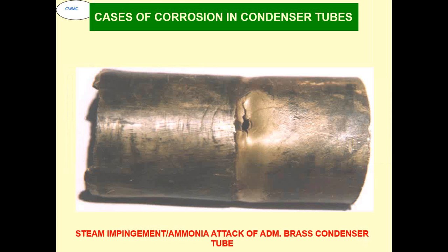This is the steam impingement plus ammonia attack on admiralty brass condenser tube. Normally, on the boiler side, we give a treatment of ammonia. Now that ammonia, when it comes to the condensate, starts trickling down on the condenser tube, and if it is a brass tube, at the baffle point, it starts concentrating, and then ultimately it will lead to the corrosion of the condenser tube. That is known as the steam impingement, ammonia grooving.